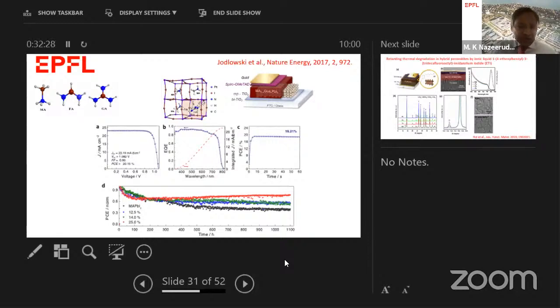The cell configuration is, as we discussed previously, the NIP configuration. The power conversion efficiency is in the range of 20%. But if you look at the stability data, that's a red line, with 25% of guanidinium, and compared with the black line, which is our reference sample, over 1,000 hours, the stability is remarkably stable, having guanidinium as an additive. So why is this happening? It's because of enhanced hydrogen bonding coming from the guanidinium. So this shows the stable performance from compositional engineering.